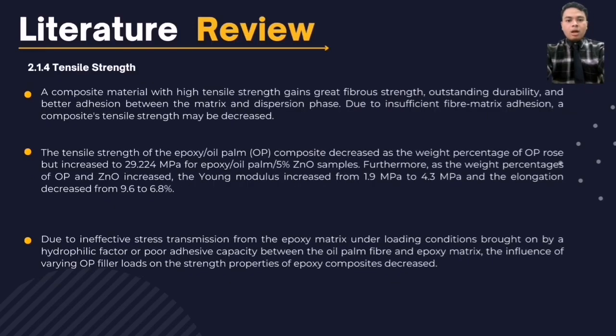For the tensile strength, a composite material with high tensile strength gains great fibrous strength, outstanding durability, and better adhesion between the matrix and the fiber phase. Due to insufficient fiber matrix adhesion, a composite's tensile strength may be decreased. Hassan and Ali 2022 published the effect of reinforcing epoxy composite with a filler derived from chopped agricultural waste from oil palm. According to the findings of this study, the tensile strength of the epoxy plus oil palm composite decreased as the weight percentage of oil palm rose but increased to 29.224 MPa for epoxy plus oil palm plus 5% zinc oxide samples.